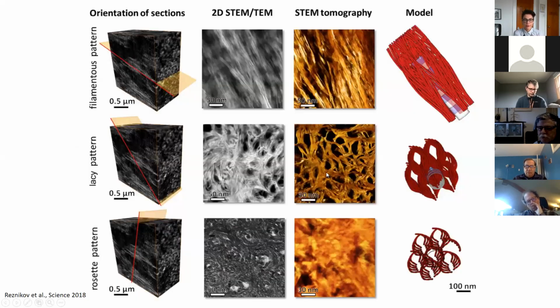And the fact that instead of having 2 views of the same structure, like on face and profile, we obtained 3 views of the same thing. The only model that could explain the coexistence of 3 motifs of mineral packing in bone would be the model of superhelical assembly of very thin and merging crystalline particles. And we call that the cross-fibrillar mineralization model.